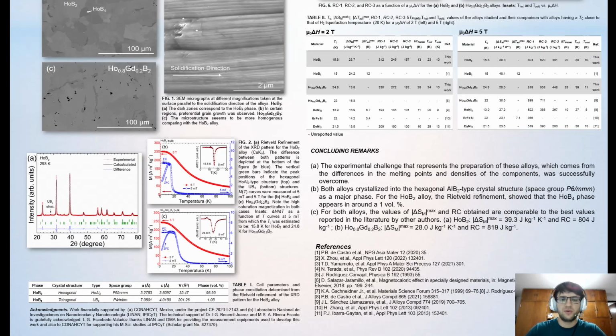Now, through X-ray diffraction analysis, it was determined that the main phase in both alloys has a hexagonal crystal structure with a space group P6/mmm. Holmium tetraboride was also detected as an impurity phase. Figure 2a shows the Rietveld refinement for the holmium diboride alloy, indicating that the aluminum diboride type crystal structure is the predominant phase with a volumetric presence of 98.95%, while the remainder corresponds to the uranium boron 4 type structure. In table 1, we summarize the information for these two phases, including the crystal structure, space group, and lattice parameters.